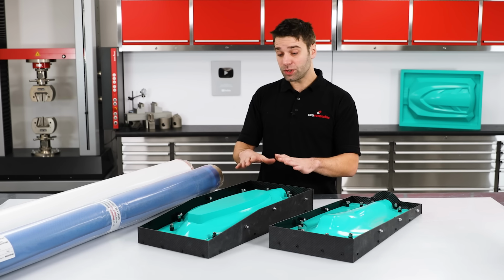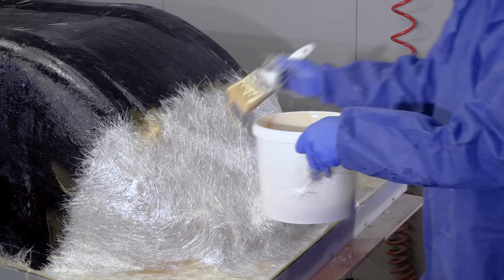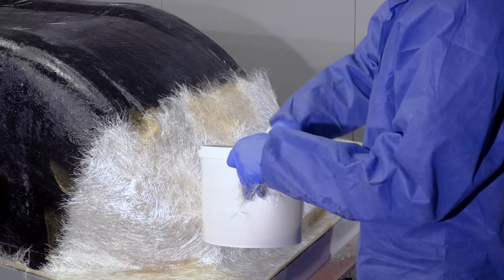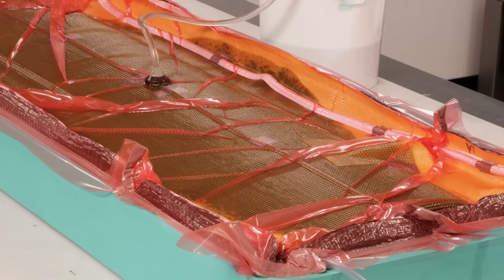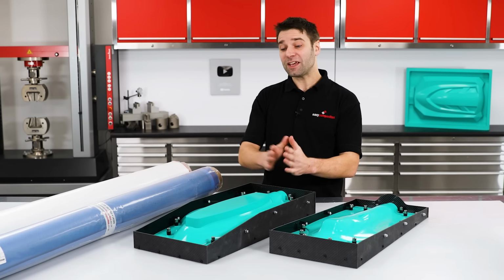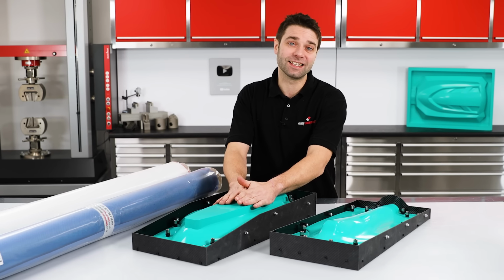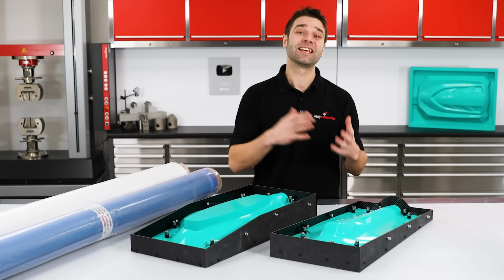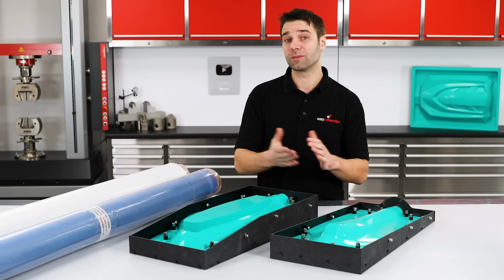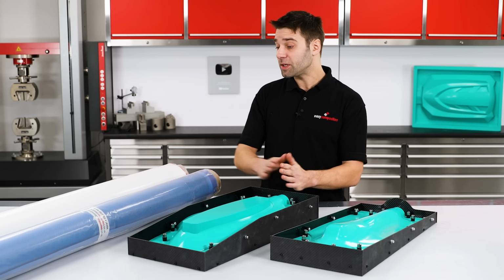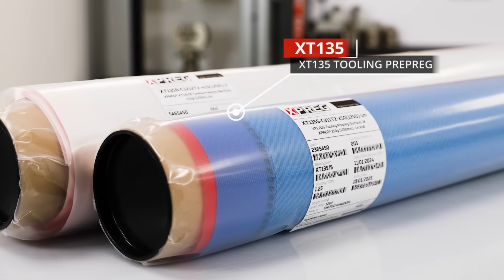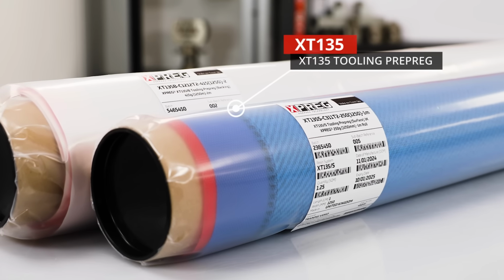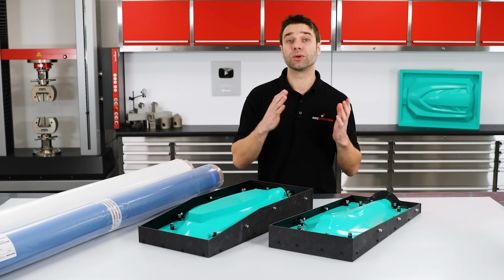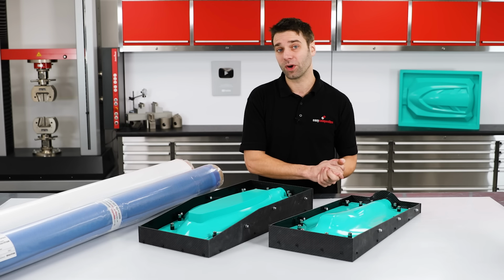In theory, you could use a pattern made in this way with the bushes for a wet layup system like Unimold, or even a resin infusion using a high temperature epoxy. But in reality, for a mould of this size and detail intended to make pre-preg parts, then a pre-preg tooling system is going to be the obvious choice. I'm going to be using the out of autoclave XT135 prepreg, but the methods used here would apply equally to an autoclave system such as the XT180.